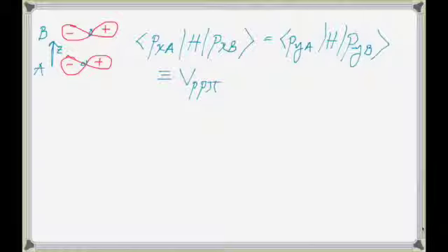Yeah, it is less than 0 because the positive lobes line up, the negative lobes line up. So the multiplication of the two wave functions is going to give you something positive, and the potential is negative. So that is less than 0. When we do the overlap integral, the only dependence on that polar angle, if you go back and look at the Y_lms, they had a sine or cosine of theta, and then an e to the plus or minus i m phi. So the only dependence on that angle phi is that exponential term.